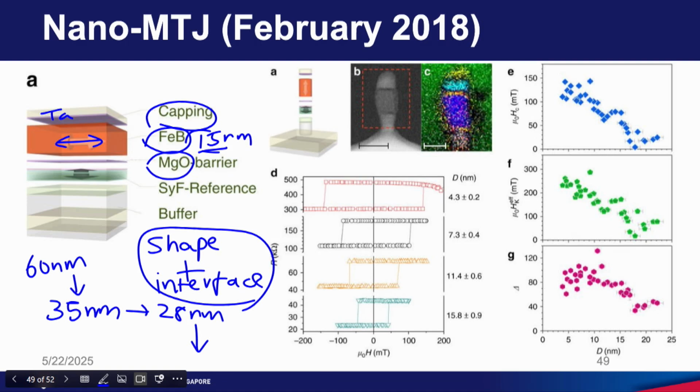But in this study, what they have done is they made lithography in such a way that they can make a kind of cylinder. We know that when we have a cylinder, the z-axis is in the perpendicular direction, I mean along the length direction. Because they made this so small, because of the shape anisotropy, this magnetization is now pointing in the up direction.